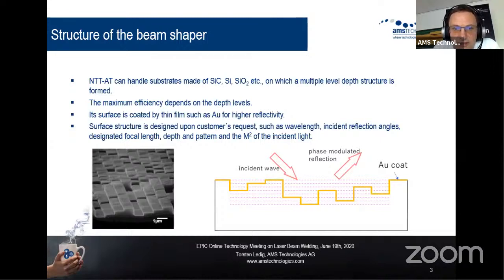So what you can do here is, for instance, to have a gold layer on such a device, and you can reach about 97% reflectivity approximately, so that only 3% are absorbed in such a device. And the surface of the structure can be designed upon the customer's requests, like wavelengths. We heard today a little bit on different wavelengths which are used nowadays for laser beam welding applications. And it can, of course, be designed according to the designated focal depths and the M² of the incident beam.